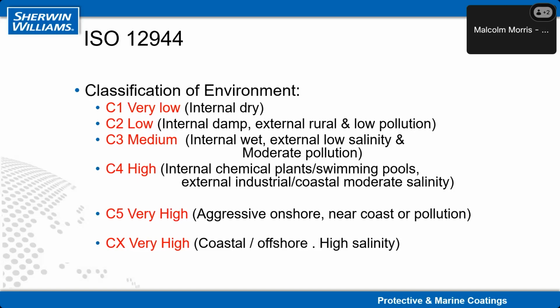C3 will be a typical urban environment. It could be an internal wet environment, such as a kitchen where you get a lot of condensation. Going to scale again, C4 will be high, so that will be an external environment getting close to the coast where you've got some salinity blowing in from the sea air. It could be an internal, very wet environment like a chemical plant or a swimming pool. Then you've got C5, which is very high corrosivity, so that would be a marine environment on the coast or very highly polluted in a chemical works or whatever. And then CX, X stands for extreme, which is very high offshore, so that will be an offshore oil or gas rig, for example, where you've got very, very high salinity and being lashed by the sea.